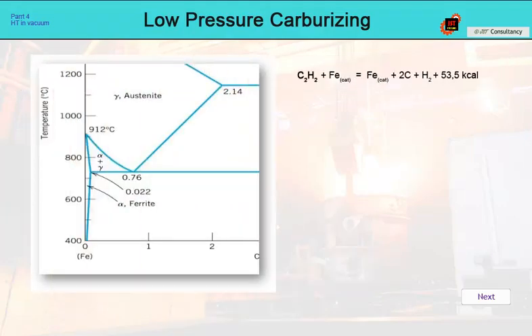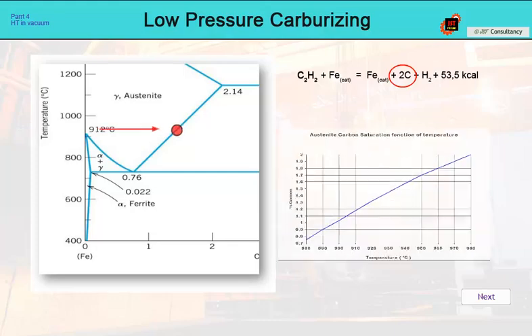Acetylene decomposes by catalytic reaction with the surface of iron into carbon and hydrogen. The expected reactions are as follows. The released carbon from these reactions is absorbed on the surface and then begins to saturate the austenite. The solubility of carbon in austenite is high, up to 2.1%, but it is not unlimited. Its limitation is given by the ACM line, which represents the formation of iron carbide Fe3C cementite. The position on the ACM line is determined by the temperature of the process.